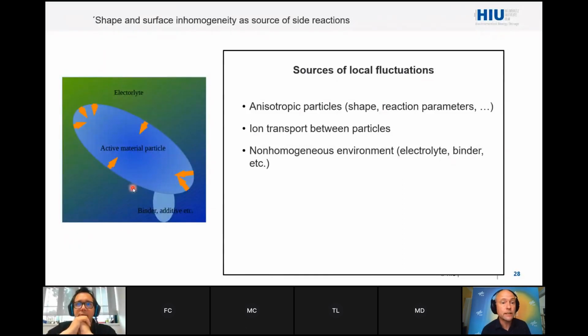The reason is that even under homogeneous situations, you will, due to the different curvatures, have a stronger increase of concentration at a part with a larger curvature and a smaller increase in regions with a smaller curvature. Of course, there's diffusion.